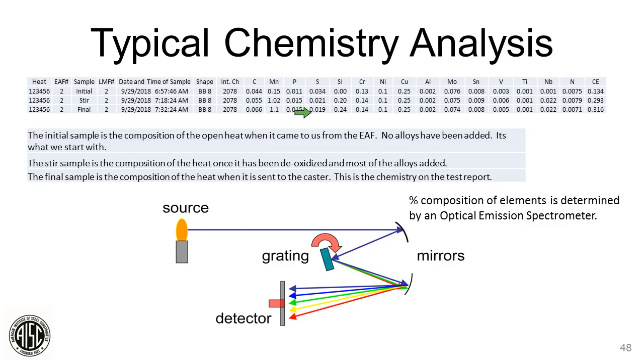We're working that down by the slag additions that we're adding. At the same time, right next to it, the silicon. We're adding silicon to kill the heat, and you see it had none before, then we add it when we get to 0.20, which is typically the silicon level we run at. So that's the heat as it's being progressed in time and the elemental adds we make to get the properties of the steel that we want. Next slide, please.